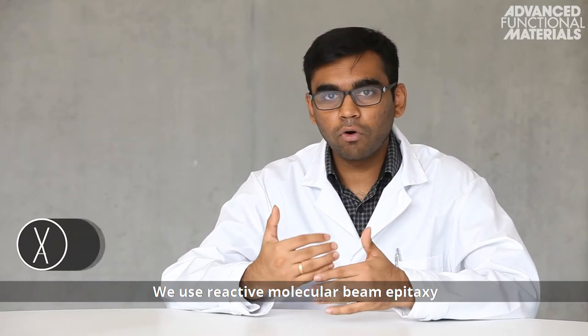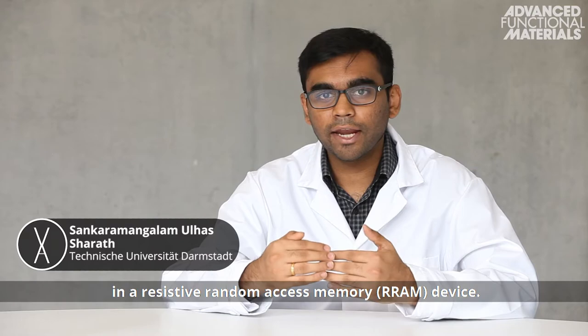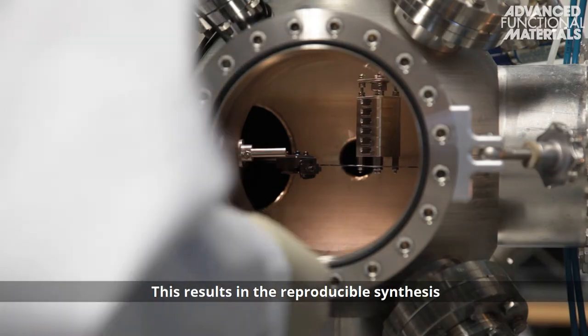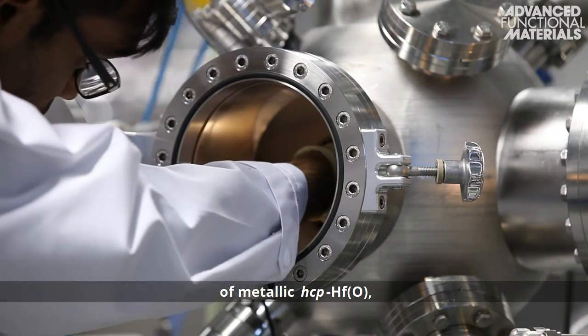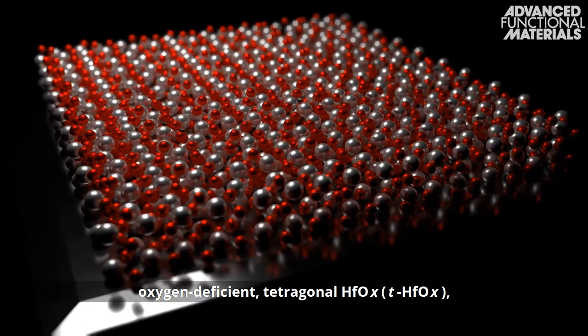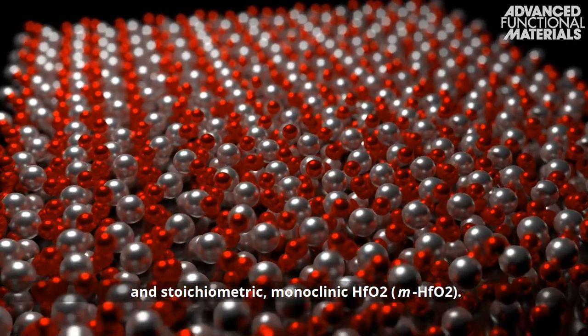We use reactive molecular beam epitaxy to change the oxygen stoichiometry in a resistive random access memory device. This results in the reproducible synthesis of metallic hexagonal close-packed hafnium oxide, oxygen-deficient tetragonal hafnium oxide, and stoichiometric monoclinic hafnium dioxide.